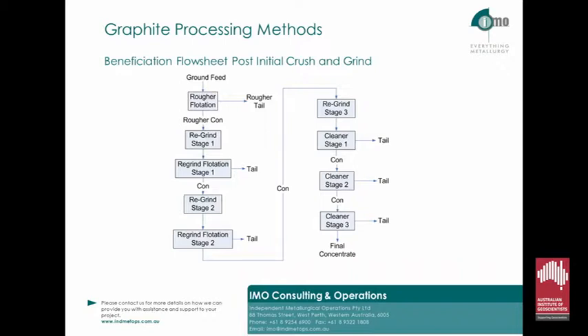This flow sheet is a good starting point for a rougher regrind cleaner test, which at IMO we've been able to generate first time a greater than 96% total graphitic carbon concentrate for a number of samples now, and even a greater than 98% total graphitic carbon concentrate on certain well-liberated samples. I'll go into more detail in the next slide why we have multiple cleaning stages after the regrind stage 3 and only a single stage after regrind stage 1 and 2.